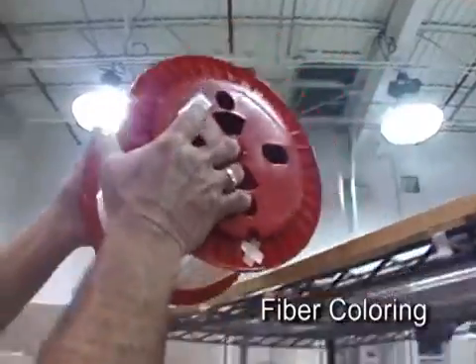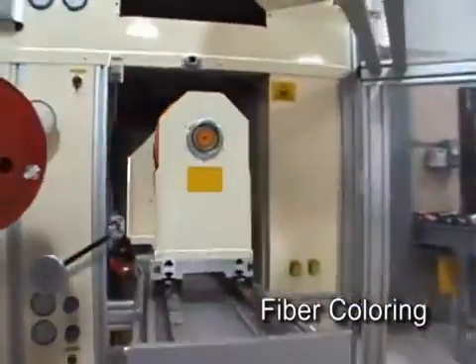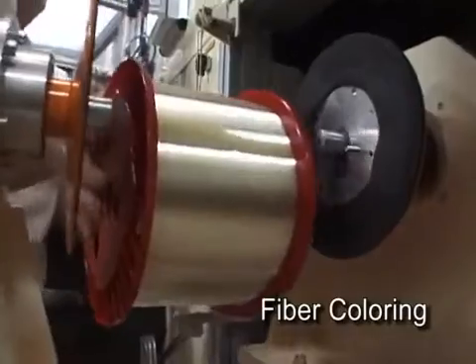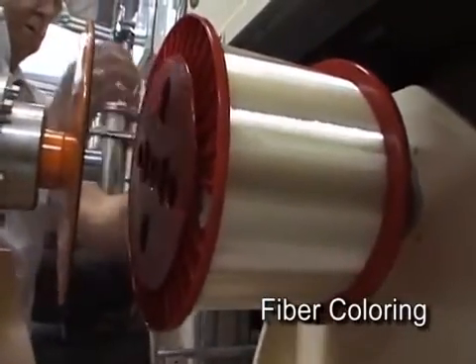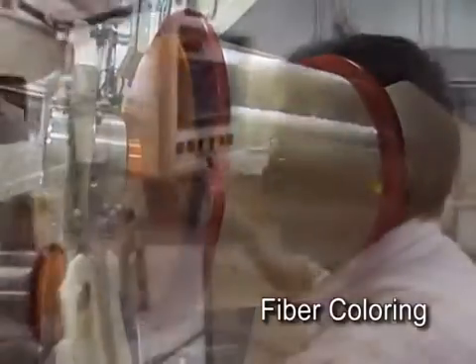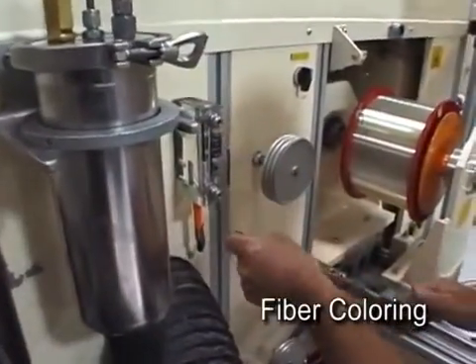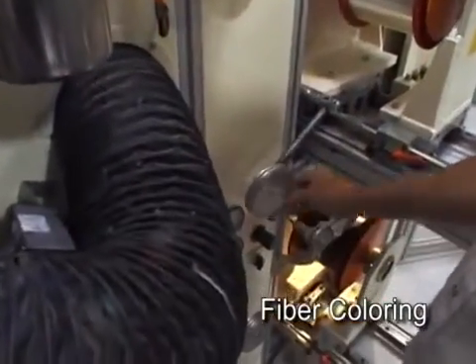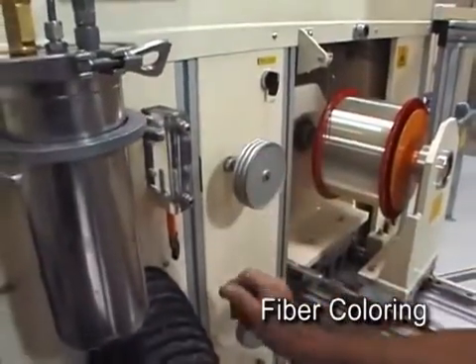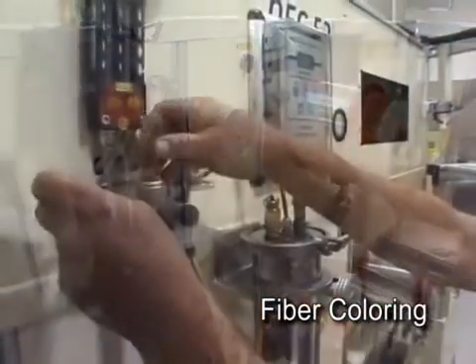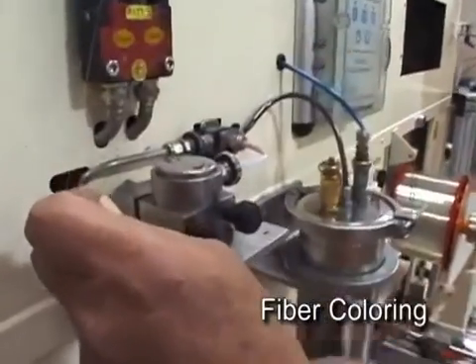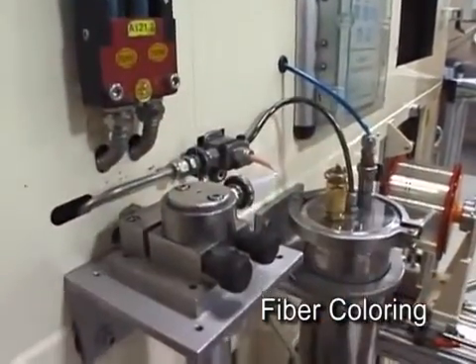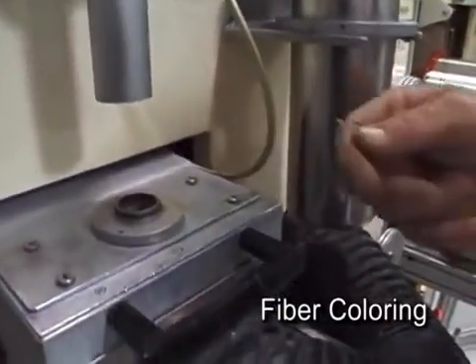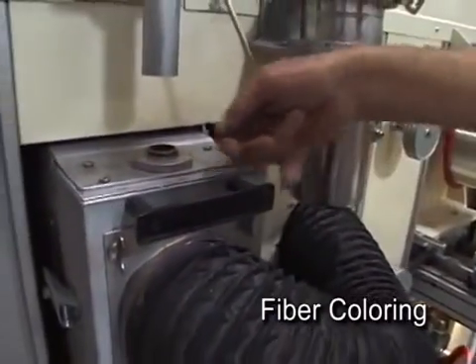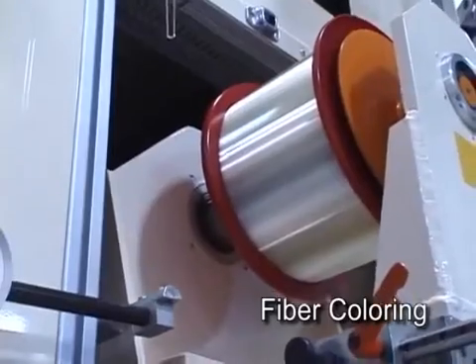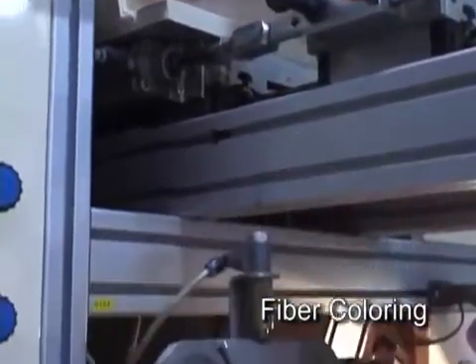The clear glass fibers initially undergo one of two types of coloring processes: UV inking, which colors it in preparation for ribbonizing and loose tube processes, or tight buffering, which provides both color and a protective coating. In the UV inking process, a specialized ink is coated onto each optical fiber. One of 12 colors is used to properly identify the optical fiber within the tube or ribbon in accordance with industry standards. After the inking step, the optical fiber quickly passes to a curing enclosure that rapidly cures the ink to form a permanent color coating and is then wound onto a take-up reel.